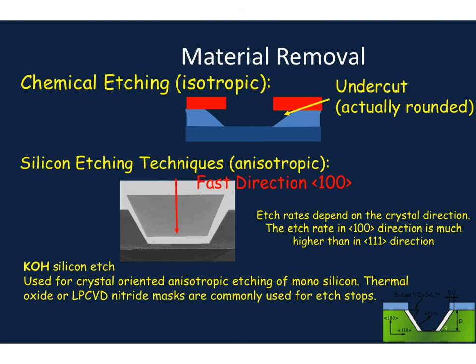And when you apply this chemical etch, like a solvent that you apply, then you get these somewhat rounded walls here. You can also do silicon etching techniques, which give you anisotropic etching, and thus allow you to go a little bit deeper to get higher aspect ratios. Here, you have a certain direction in which you have the fastest removal of material. And the etch rates depend on the crystal direction. So in this case, the etch rate in this vertical 100 direction is much higher than in the lateral directions.